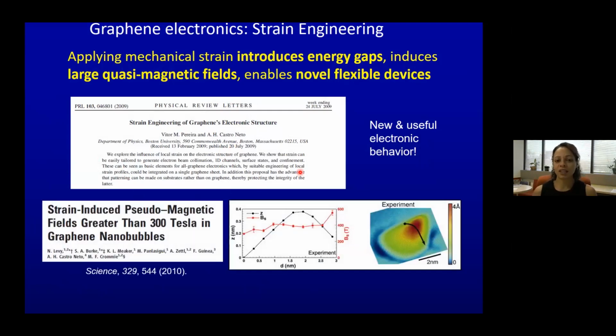And here I'm going to give an example, which I think is one of the best examples of how to modify material properties with strain. This was a scanning tunneling microscopy experiment where graphene was just put on a surface and they happened to find little nano bubbles on the surface, of the order of a couple nanometers in height. Then they did scanning tunneling spectroscopy on top of these bubbles. And they found the electrons were circulating around these bubbles in the same way that they'd circulate in an ultra high magnetic field. So around this strange graphene, the electrons were moving as if they were in a 300 Tesla magnetic field. That's a huge magnetic field.